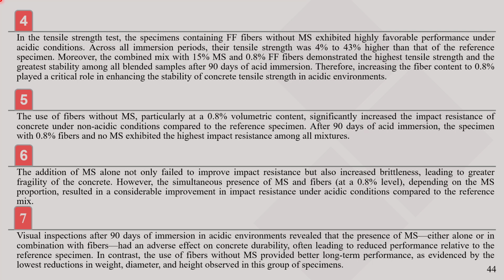Additionally, the energy required to initiate the first crack and to reach complete failure decreased significantly with microsilica, making the samples more brittle. In terms of visual deformation, the trend was similar. Using microsilica alone under acidic conditions reduced performance relative to the reference, while fibers without microsilica provided better long-term performance, resulting in the smallest reductions in weight, diameter, and height.